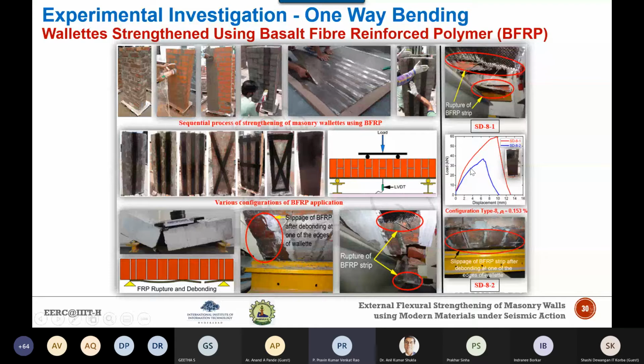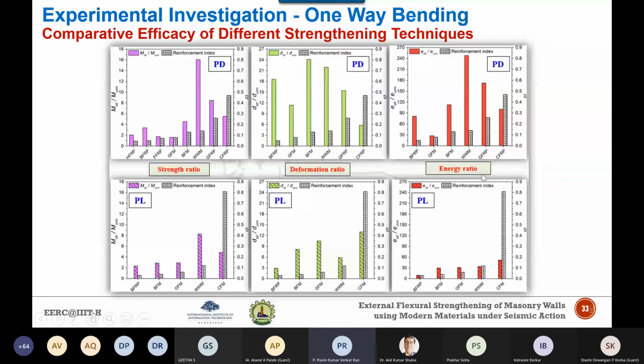Now, if you see this bar chart, you can see that all these strengthening techniques have shown an enhancement, not only in the flexural strength, but also in other properties. Here on the y-axis, this is a ratio of the strengthened masonry to that of the unreinforced masonry. The x-axis is basically showing the type of different strengthening techniques which have been applied in the present study, and also we have collected some of the test results and normalized them in order to have a better understanding. So this is the strength ratio. Similarly, this is the deformation ratio. So this is the deformation of the strengthened specimen to that of the unreinforced masonry specimen. And next is the energy ratio. So few curves for perpendicular to bed joints, few bar charts for the parallel to bed joints.